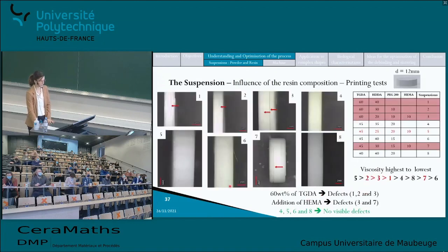So samples 1, 2, 3 and 7 presented big cracks and delamination, whereas samples 4, 5, 6, and 8 appeared to be defect-free in this experiment. Here, all of the suspensions prepared with 60% of TGDA presented cracks and delamination, but these suspensions were also the ones with the highest viscosity. So this defect could have actually appeared during the printing process.